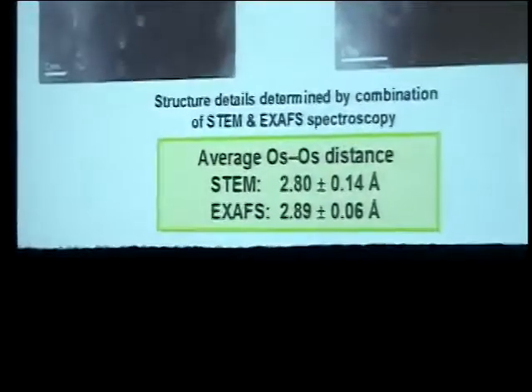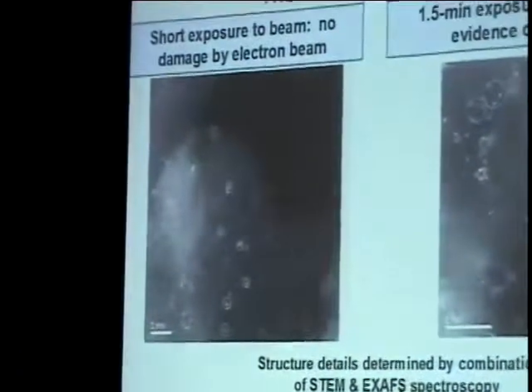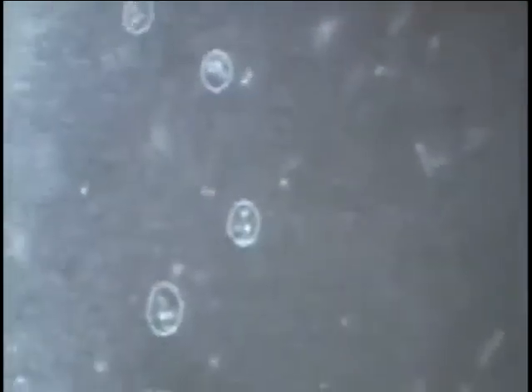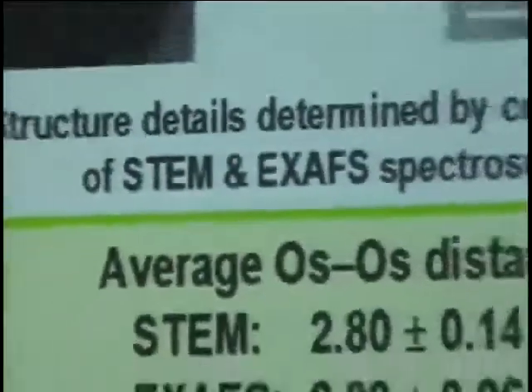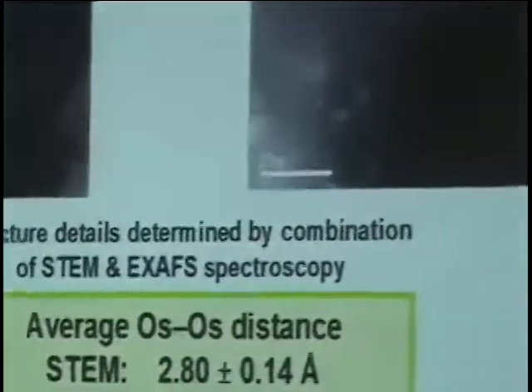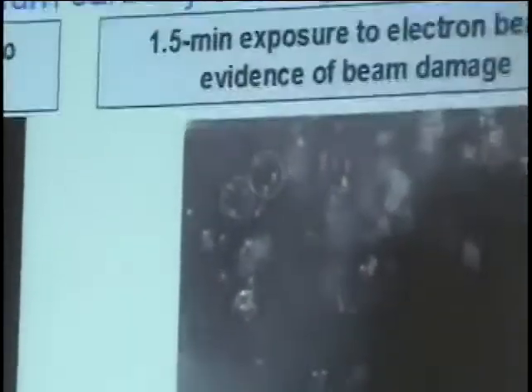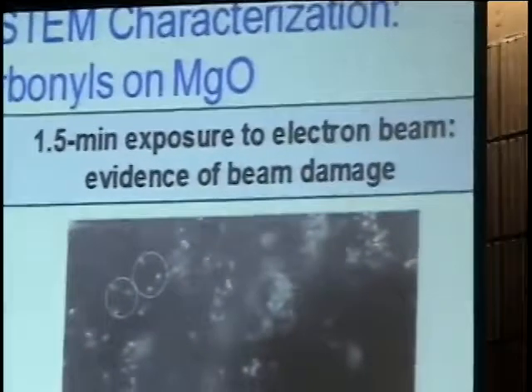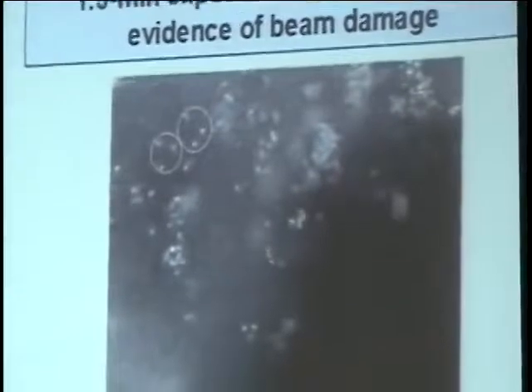And what you see on the left now is that we have resolution. I hope you can see it in the back. We can see the three atoms in the three-atom clusters nicely resolved, and we can determine the average osmium-osmium distance, which is this. And then by XAFS spectroscopy, from the osmium-osmium contribution in the EXAFS, we can determine the average osmium-osmium distance. And within the error, those two are agreeing.